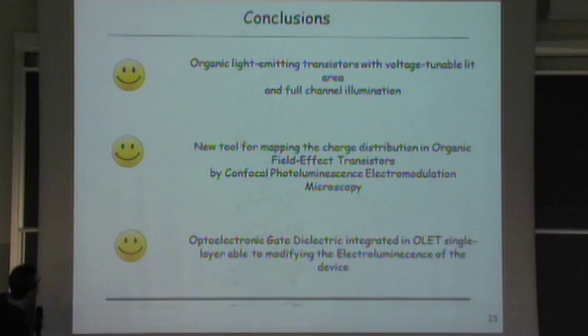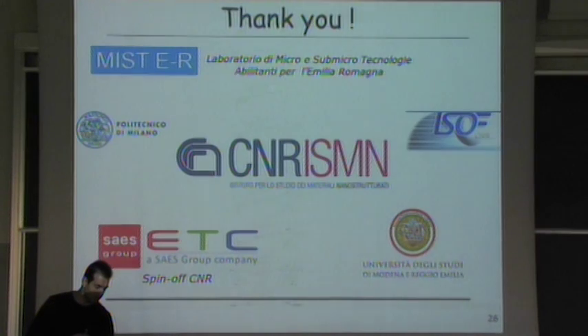To conclude, we have now an organic light emitting transistor with voltage tunable lit area and full channel illumination. We have implemented a new tool for mapping the charge distribution in organic field effect transistors by confocal photoluminescence electromodulation microscopy. And also we have a new optoelectronic gate dielectric to integrate in this kind of devices, and it is able to modify the electroluminescence of the device, so it's a good point.